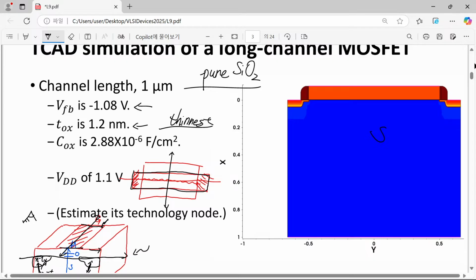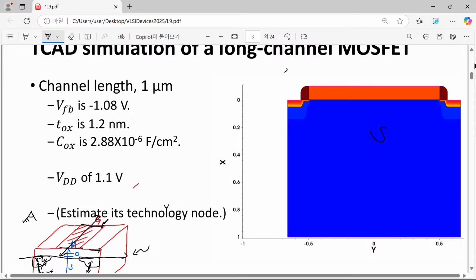For example, 0.5, that is possible. However, when you make such a thin oxide, your device is no longer working as a good transistor. That's the reason why people just scaled down their oxide thickness down to 1.2 nanometer. So after that, what happened? After that, they tried an even thinner oxide, but they failed. So after that, they introduced a different high-K oxide here. So high-K insulators were introduced in this scene. So please remember that if the pure oxide is so thin like 1.2.